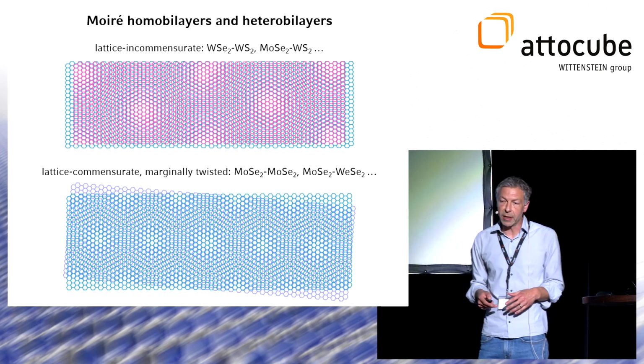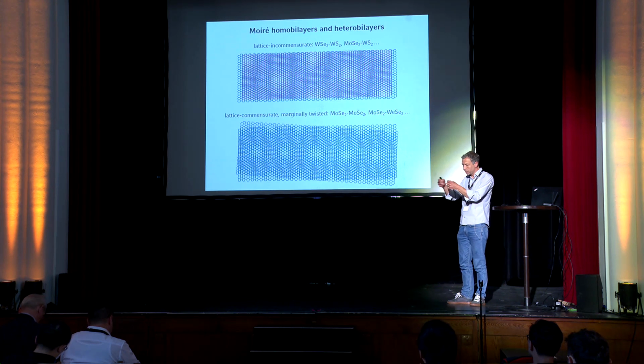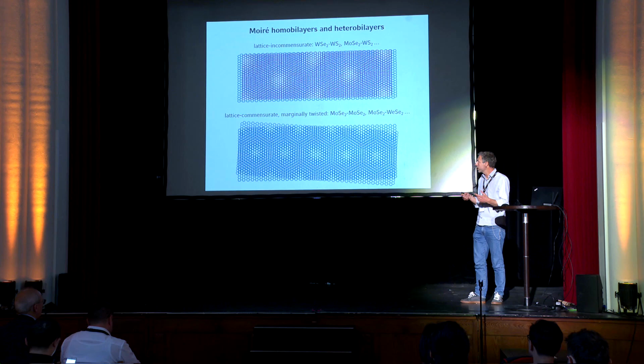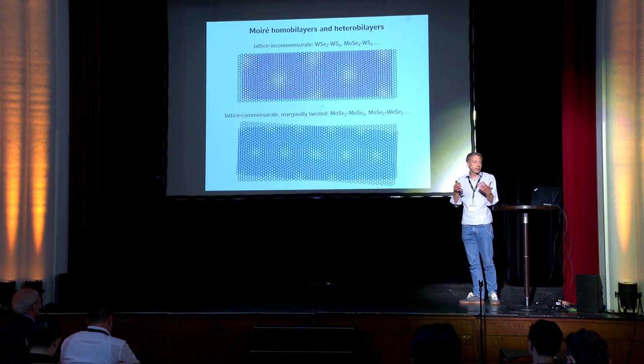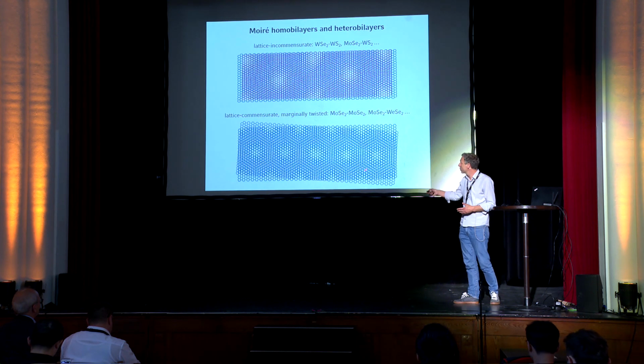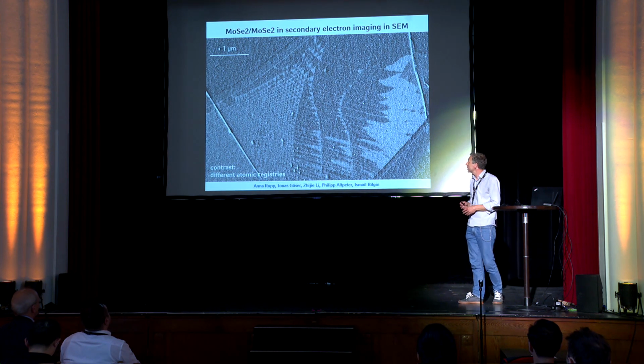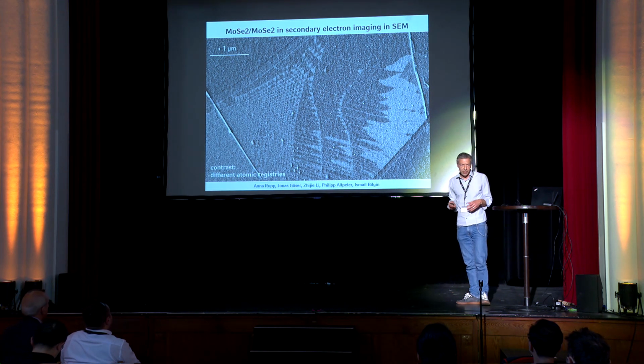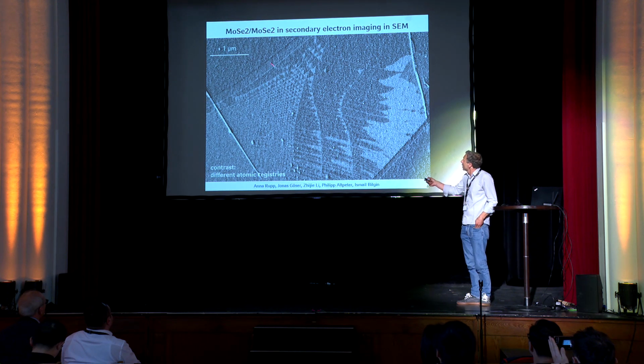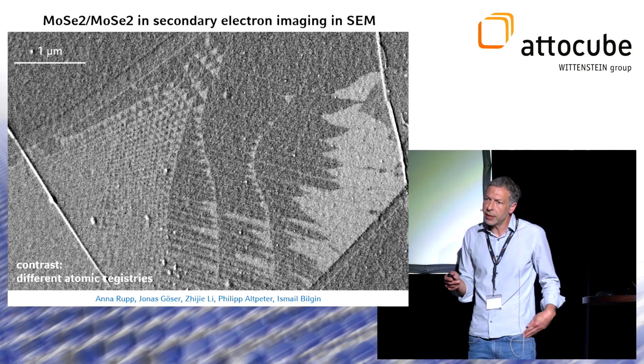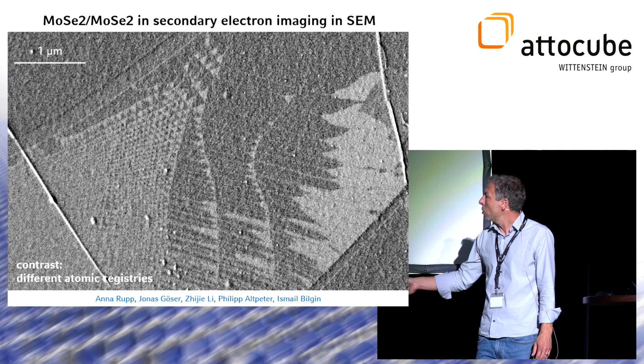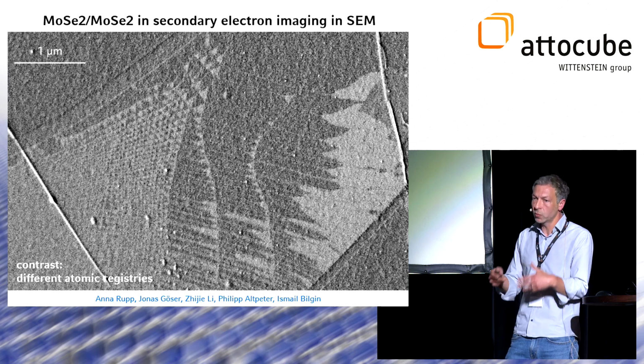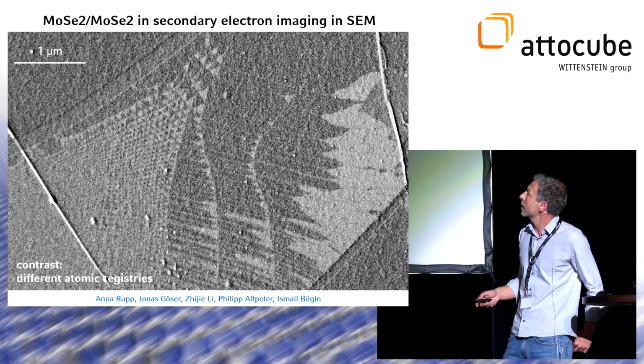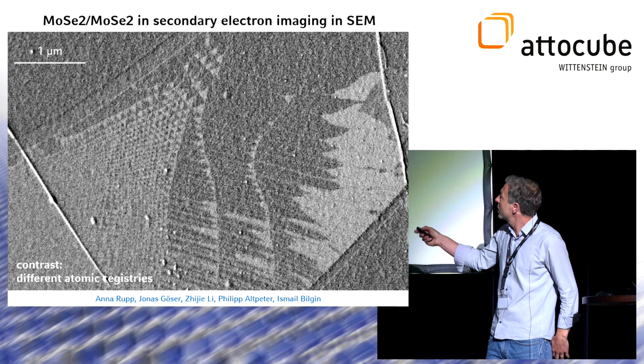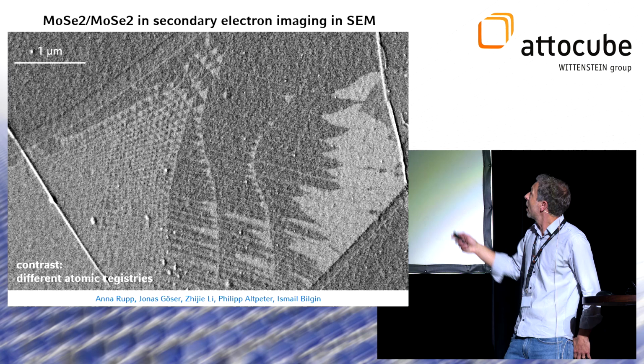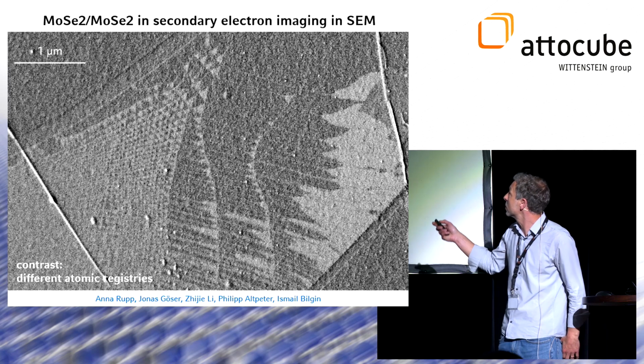Instead, there is a very fundamental effect kicking in where the lattice atoms rearrange or reconstruct to form patterns that are unexpected from this notion of PowerPoint moiré. So let me start out with this, and this is a reality that we have seen on many samples. This particular example is a molydiselenide homobilayer at a very small twist angle, and the contrast here in the secondary electron image performed with a standard scanning electron microscope arises from the difference of atomic registries, high symmetry atomic registries in these gray and dark domains.